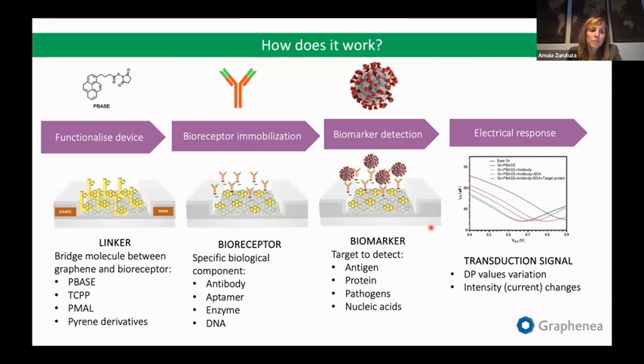There is a lot of work published on the functionalization of graphene. Initially, a lot of focus was on covalent functionalization, but now most papers have moved to the non-covalent. And why? Because covalent functionalization means you are disrupting the graphene honeycomb lattice and you are decreasing the mobility. And we said the mobility is a very important parameter for having the sensitivity there, right? So that's the reason why now most researchers have moved to the non-covalent functionalization.